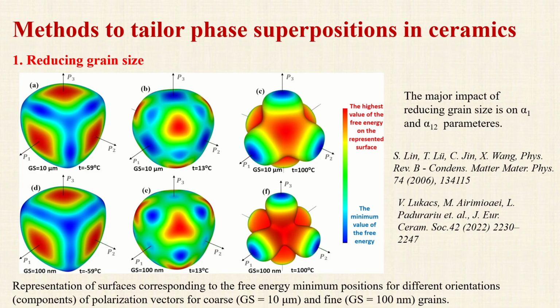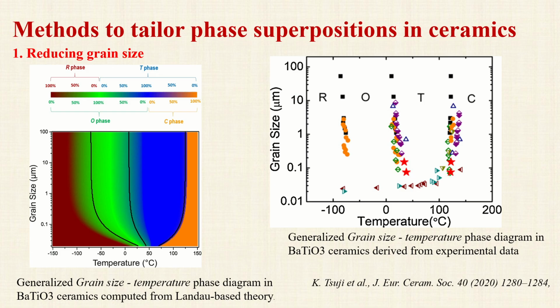These diagrams are useful to describe the appearance of phase superpositions in barium titanate with various grain sizes, but the Monte Carlo algorithm was further applied to derive qualitatively the amount of the phases at various temperatures and grain sizes. Therefore, we have proposed a more generalized phase diagram by comparison with the diagram proposed before in literature.